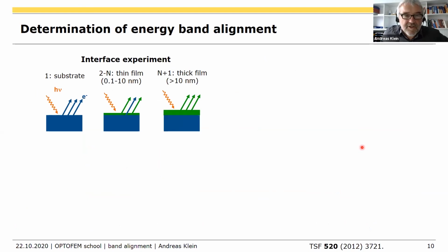Okay, now how do we determine Schottky barriers or energy band alignment? I showed this already to you. We make these interface experiments. We measure a substrate, then we measure a sample with a very thin film on top. We stepwise increase the film thickness until the film is so thick that our XPS signal from the substrate is completely attenuated. That's the ideal situation.